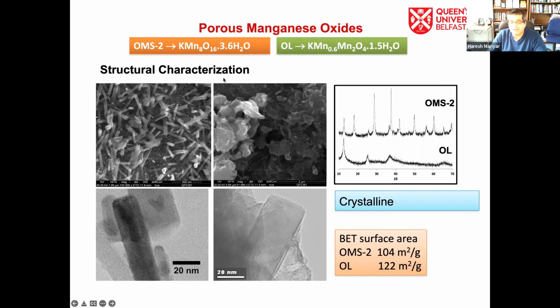A particular form of manganese oxide is octahedral manganese oxide molecular sieves. These are nanorod shaped materials. As you can see from the TEM here, we have nanorod shaped morphology. You can see nice rods here, with a diameter of around 20 nanometers. They're hollow and porous from inside, and the length can vary from 100 to 500 nanometers, and we can tune the surface area to around 100 to 120 square meters per gram.